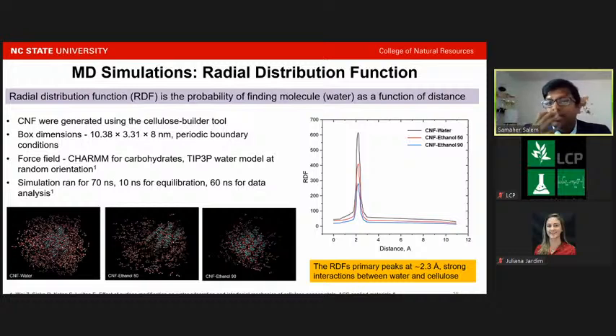So we could see that with the addition of the ethanol and with the increase of the concentration of the ethanol, the presence of water around the cellulose surface decreased. And this can also be shown by the images I captured. This correlates with all the findings we have: the NMR, the surface tension, and also the bound water and the hard-to-remove water content. And it helps to explain how the presence of this hydration shell, which is formed due to the presence of a higher amount of bound water, affects the reactivity of the nanocellulose.